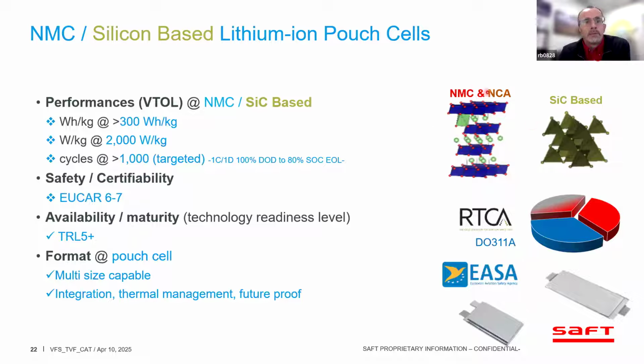There's no magic here. Your cathode is, as a 2D structure, not 3D, so destabilization there. High capability to host the silicon on the anode, and you obtain outstanding technology, a specific energy density of 300-plus watt-hours per kilo, 2000 watt per kilo, and achieve the 1000 cycles minimum. But it's a drastic change with the UCAR 6. It's a drastic change from the LMFP blend, which offered 2500 cycles, and EUCAR 3 and 4.